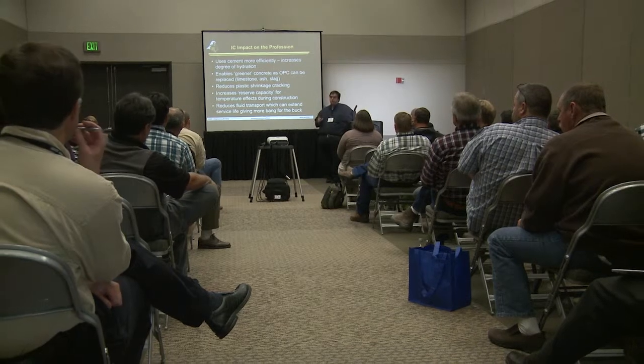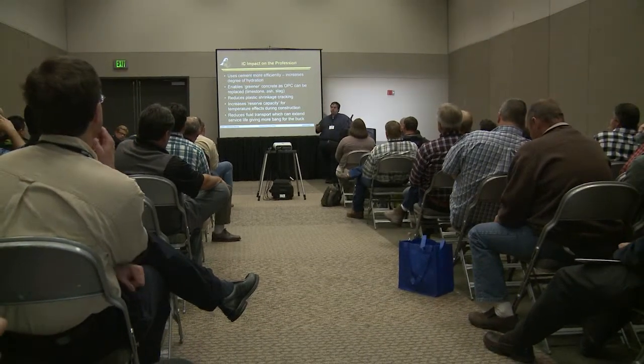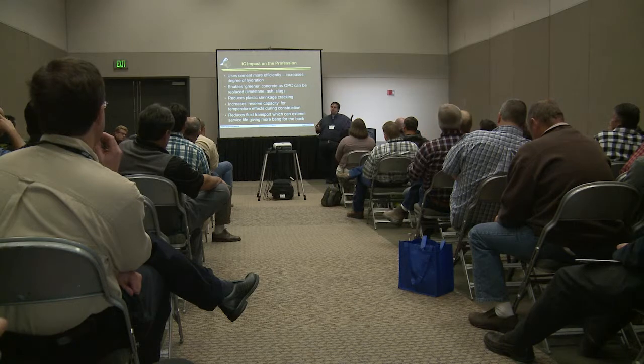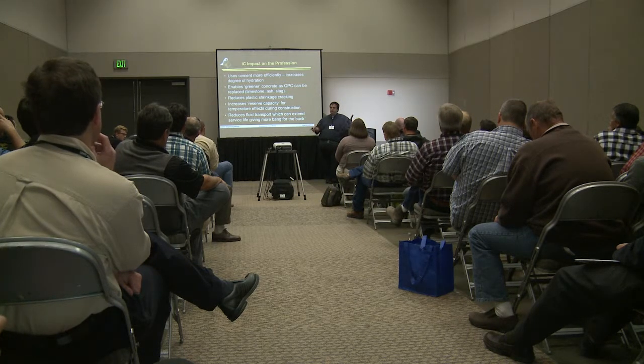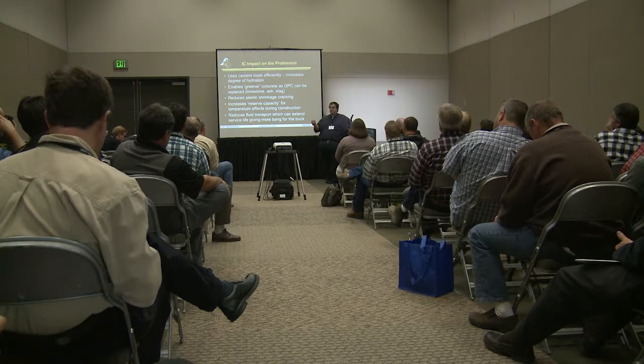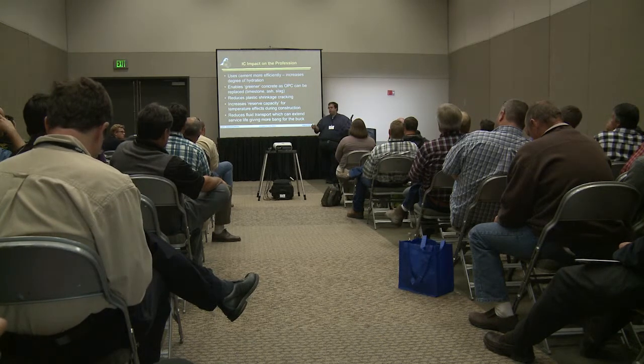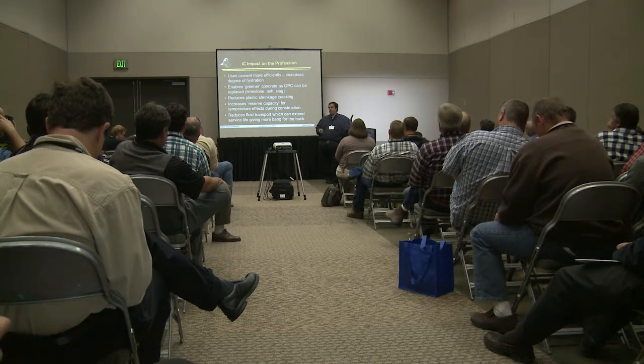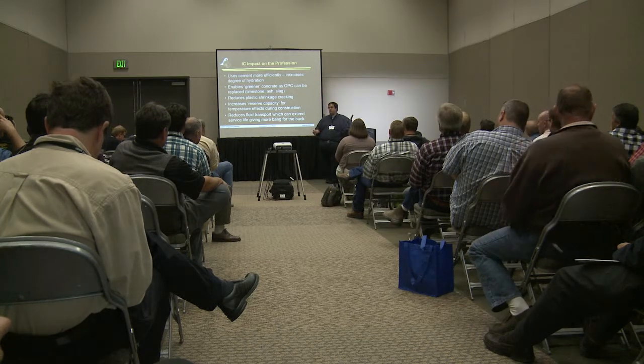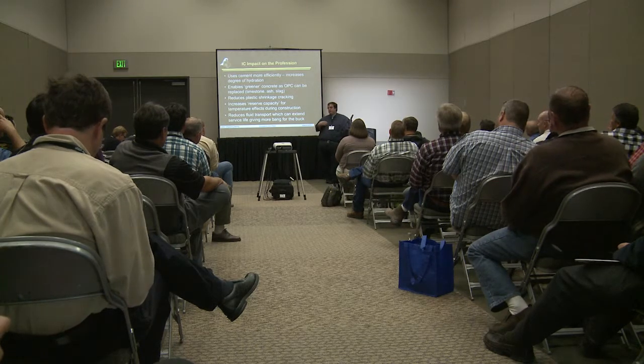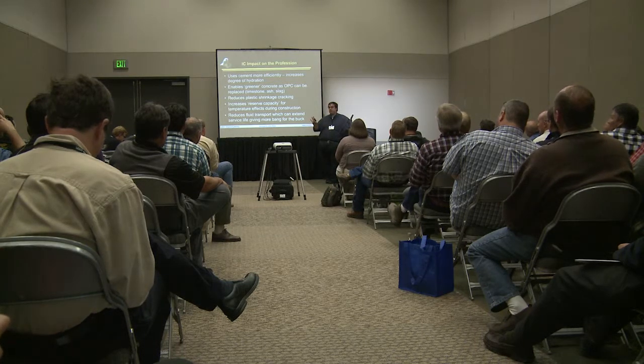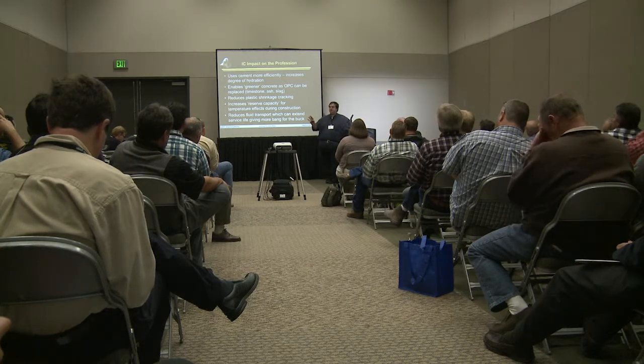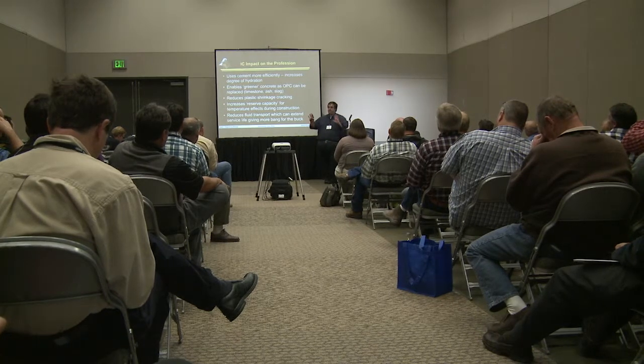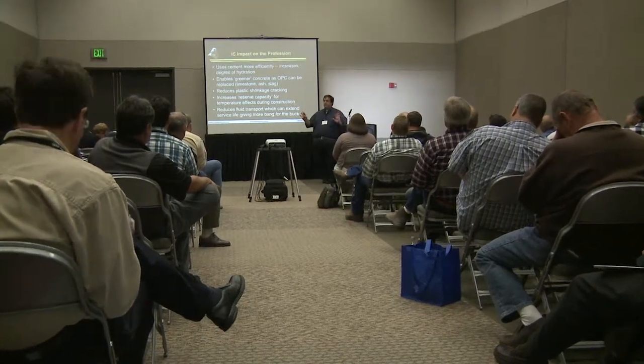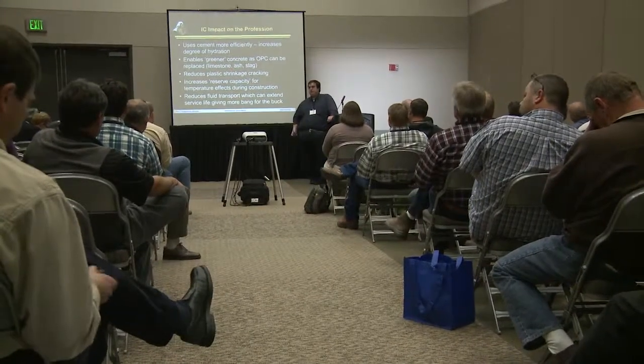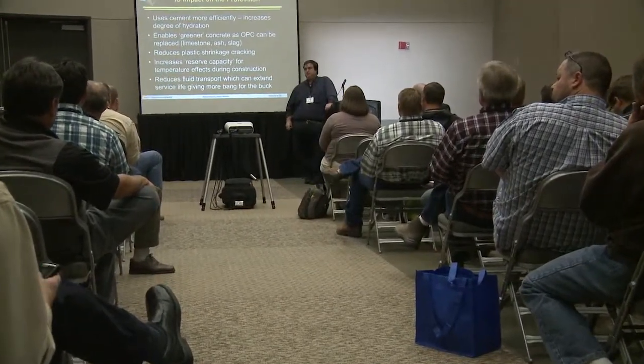concrete. But I also will point out something, that there are studies that we've been doing, there are studies that are coming out of Canada that are suggesting that you double the service life of your concrete when you do this. So if you think about this, $10 a cubic yard more, $12 a cubic yard more compared to twice as long service life, to me it's a pretty easy calculation. When I mentioned this, I was told by someone we'd have to be stupid not to do that. I didn't want to agree on the part that I would insult someone, but to me it seems to make a lot of economic sense. Okay.